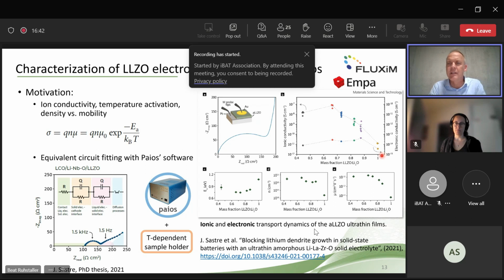And in this particular materials optimization study, a mass fraction was changed, and the ionic conductivity was monitored. The best case was the highest conductivity of ions at a composition where the electronic conductivity is still limited; that was then the best choice of material composition. So this was the first demonstration of our instrument being applied to battery research.